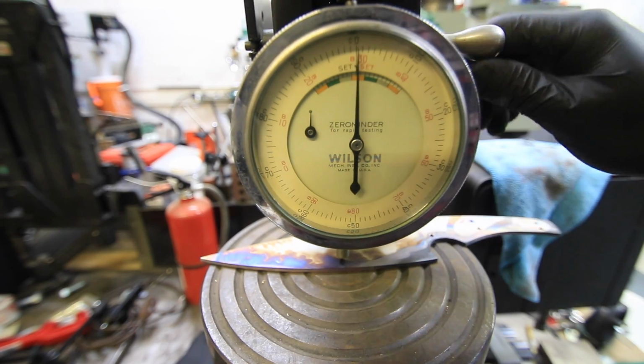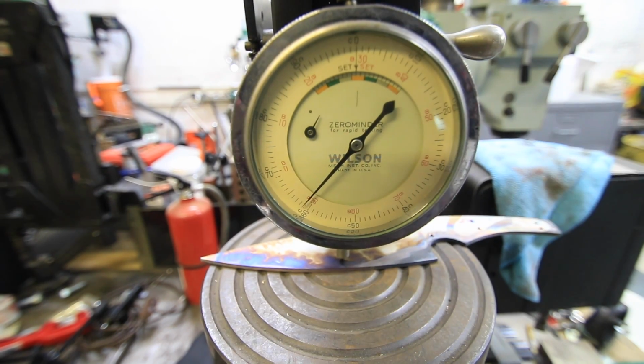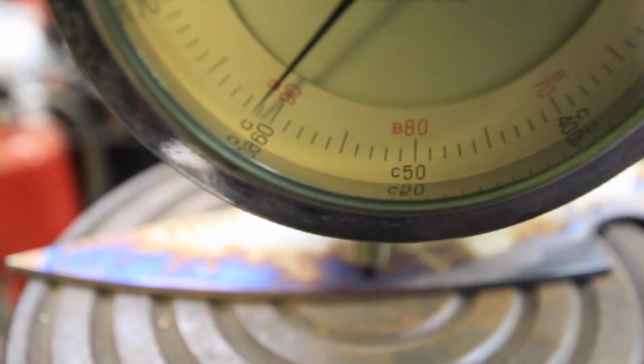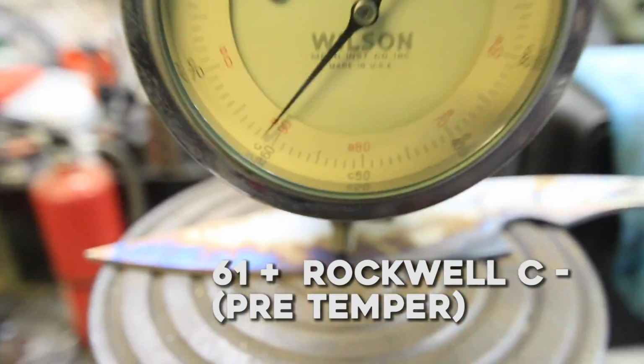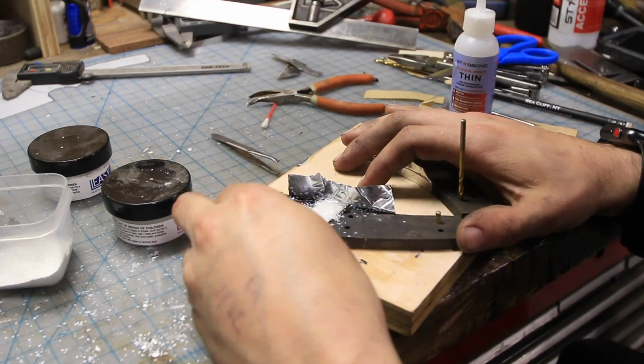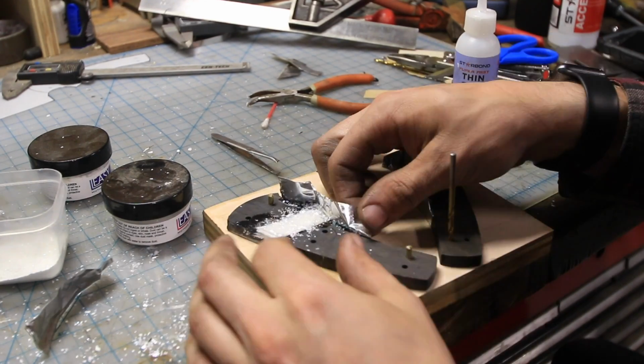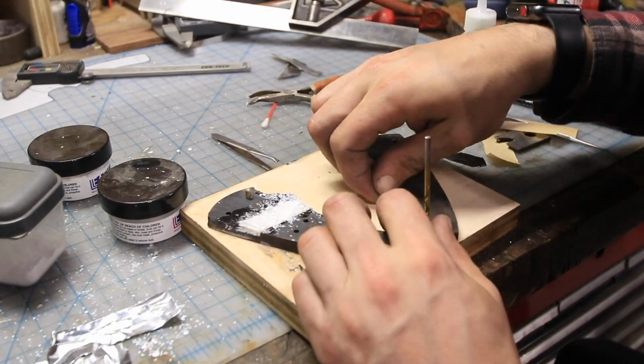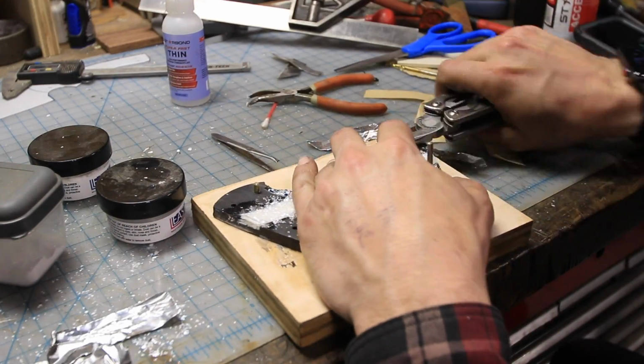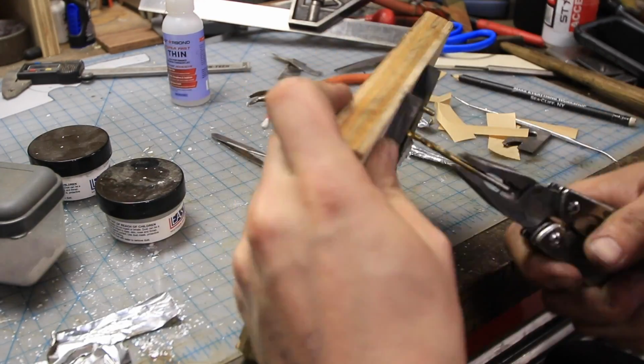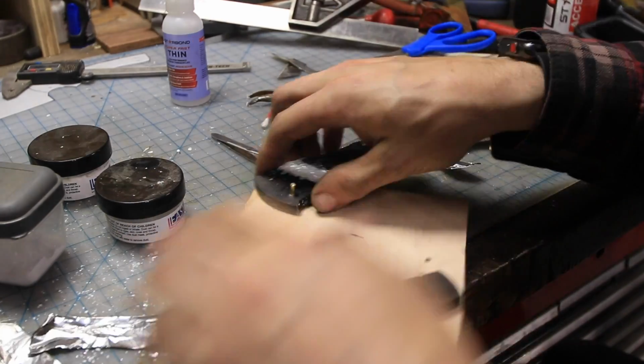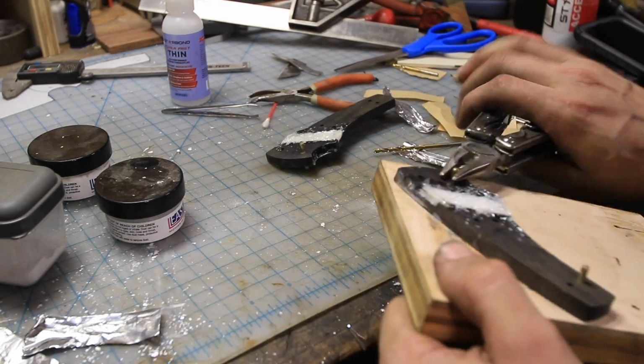any warping. Now I threw it on my Rockwell tester to see how hard the blade was before I go to temper it. I get about 61, a little higher than 61 Rockwell, which is great. I'm not going to do any cryo treatment on this just because I don't have the setup, and I'll go ahead and temper it at 425 degrees for 2 hours for 2 cycles. In the end, I wound up with a 59 Rockwell blade.